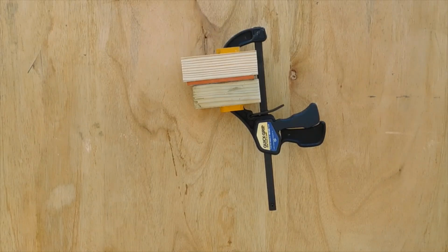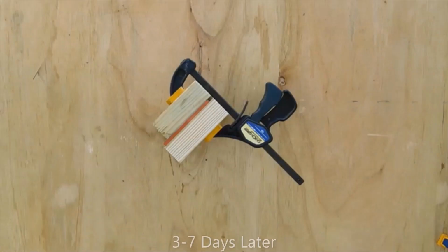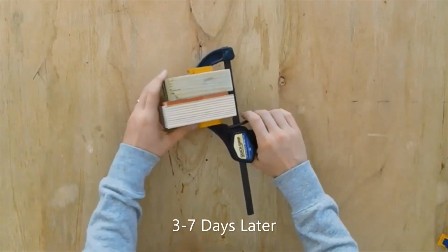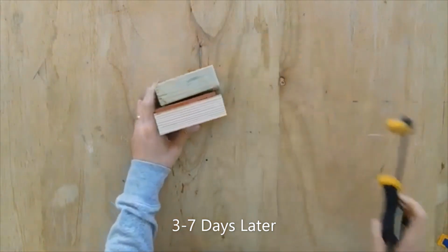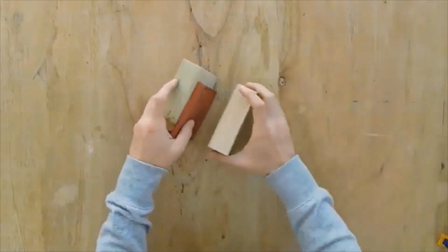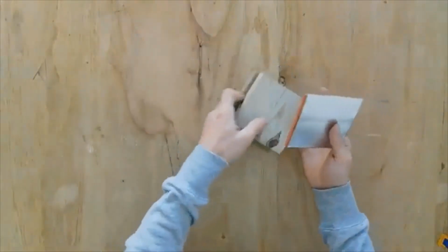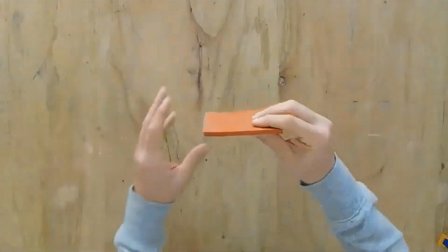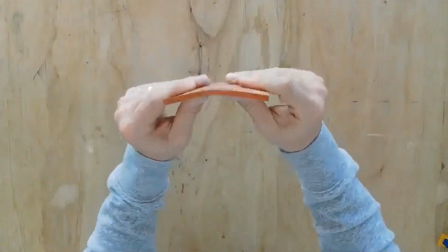If using PSA6573a, if possible, it is recommended to expose the laminate to 200 F in an oven with some light pressure for 20 seconds. Then remove from the oven and allow to cool. This helps promote optimal adhesion. If leftover catalyzed adhesive, meaning PSA blended with SRC18, store it in tightly closed containers and use within 48 hours.